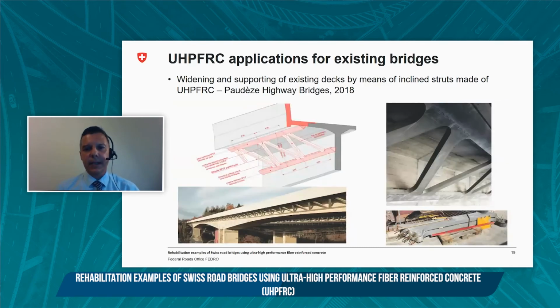The solution proposed was to widen the deck slab by ordinary reinforced concrete and support its widened cantilevers with struts, allowing to maintain the existing steel reinforcement in the slab and thus minimizing the intervention on the deck. The struts were made of ultra-high performance fiber reinforced concrete to minimize their weight and to avoid their future maintenance, which would be the case if they were made of steel. In total, 816 such inclined struts of 5 types were produced. The ultra-high performance fiber reinforced concrete struts were prefabricated, allowing thus to reduce their cost to 500 Swiss francs per unit, whereas the joints with the web of the longitudinal girders and the cantilever slabs were assured by concrete cast inside of ultra-high performance fiber reinforced concrete.